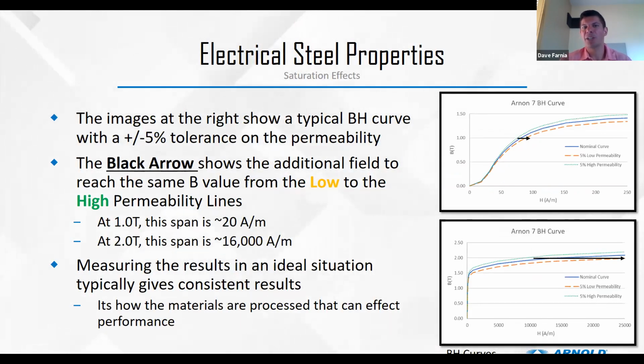So when we're talking about electrical steels, again, we make our own version of silicon steels here. They're rolled very thin, but we also have to characterize these materials. So we get typical properties, and these are usually the properties that are going to be published. So typical BH curves, that's going to be in the JMAG database. It's what we would utilize for performance predictions, relatively representative. Most of the time, when we take these measurements of the materials, there's not a lot of differentiation. But what happens is if we're processing some of these materials, we can affect some material changes.